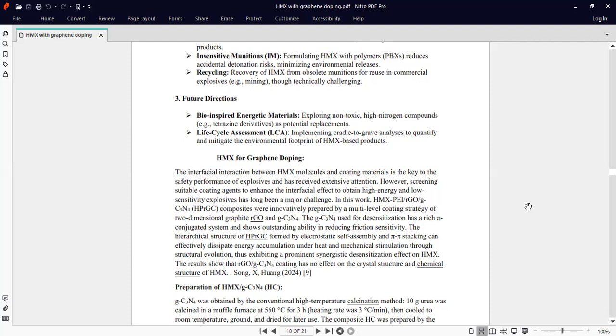In this work, HMX, PEI, rGO, g-C3N4 and HPrGC composites were innovatively prepared by a multi-level coating strategy of two-dimensional graphene and g-C3N4. The g-C3N4 used for desensitization has a rich pi-conjugated system and shows outstanding ability in reducing frictional sensitivity.